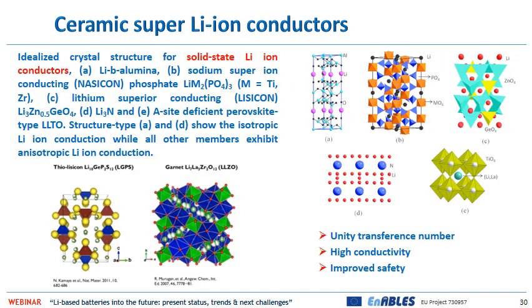Another important class of solid electrolytes are the solid inorganic materials, including ceramics and glasses, which present high lithium ionic conductivity at ambient and subambient temperatures. Particularly, superionic conducting ceramics have impressive conductivity values and are single-ion conductors, allowing the lithium transference number to approach unity. These characteristics and the absence of leakage make the inorganic electrolyte a highly appealing electrolyte material for lithium-ion batteries. However, when used in the form of pellets, they are brittle, which makes incorporation into a battery difficult.